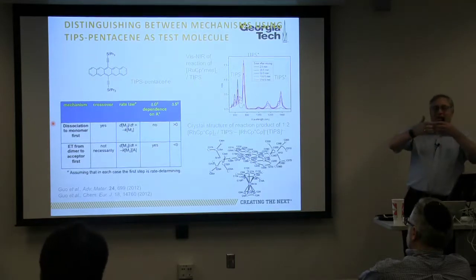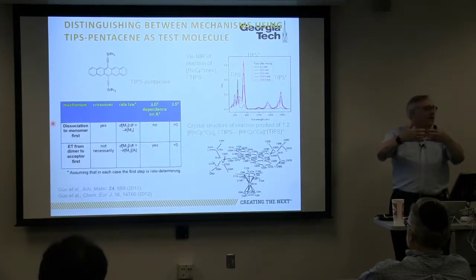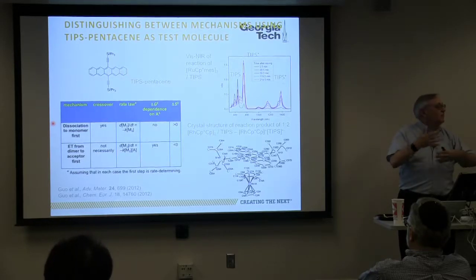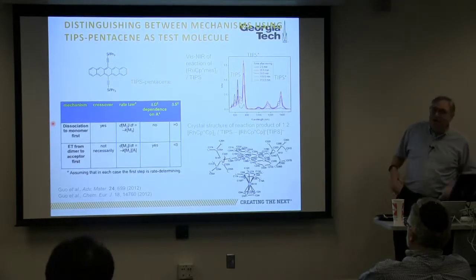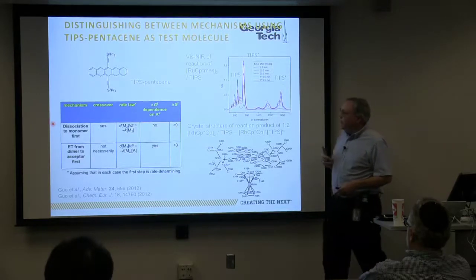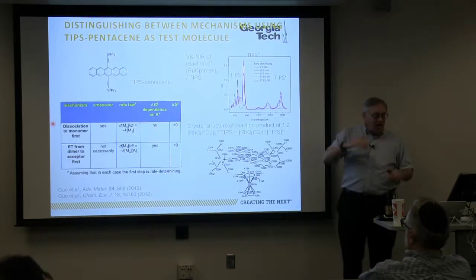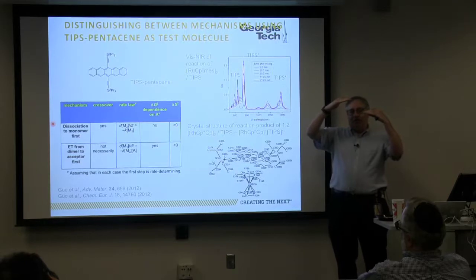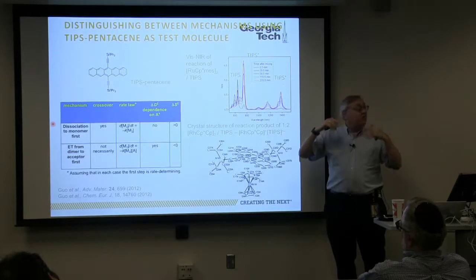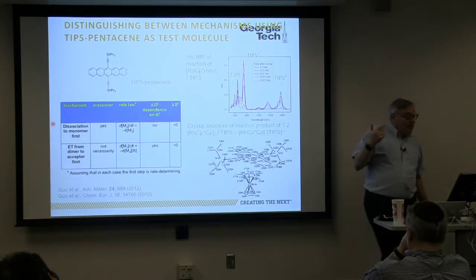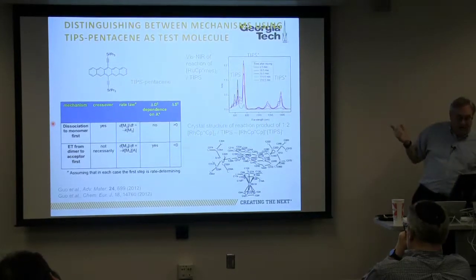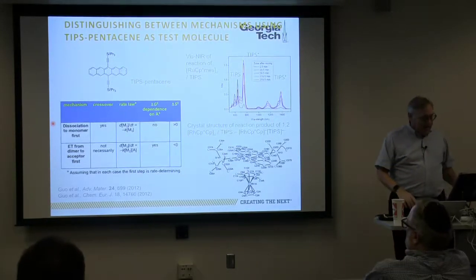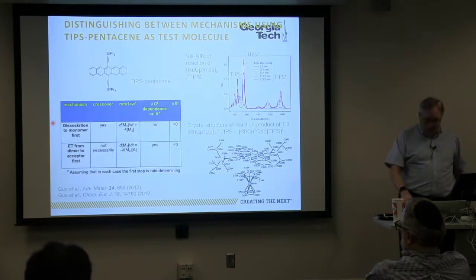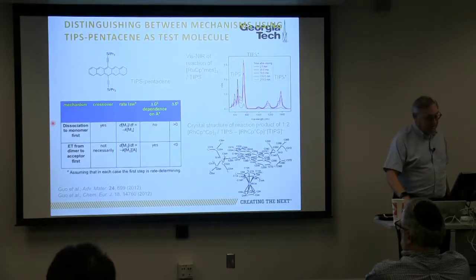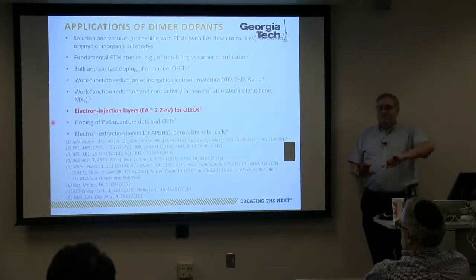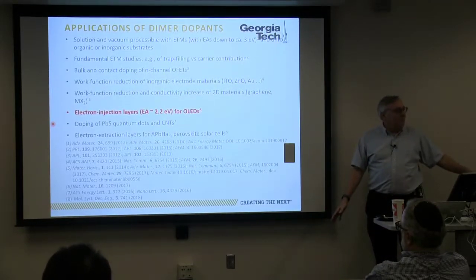One will involve things where they can come apart and come back together, and we can do experiments with isotopic labeling to look for that. We can see whether the first step has a dependence on the redox potential difference between the donor and the acceptor, which is indicative of the second mechanism, and we can look at things like the entropy of activation. With all of that, we figured out how these worked, and that gave us insight into how to go and design new materials. So that's basically it for the chemistry, more or less.